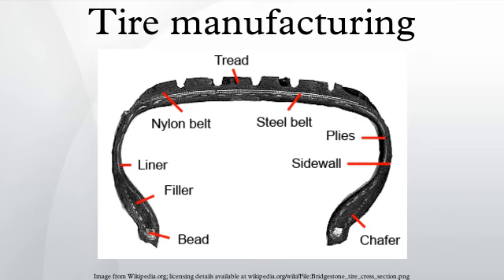Component preparation: Components fall into three classes based on manufacturing process — calendaring, extrusion, and bead building. The extruder machine consists of a screw and barrel, screw drive, heaters, and a die. The extruder applies pressure and heat, while the extruder screw also provides additional mixing of the compound through the shearing action.